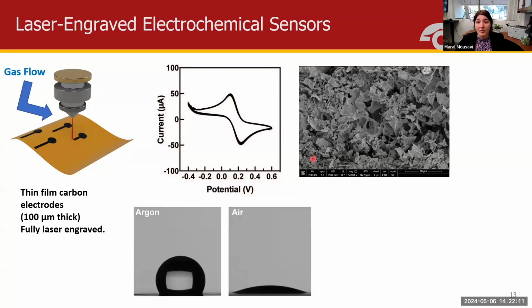We modified the surface properties of these electrodes using gas flow. So the carbonization is happening either in air or in argon, and that assists in forming a more stable interface for these specifically potentiometric systems. We're after a hydrophobic surface, so we generally do argon engraving for creating potentiometric sensors.